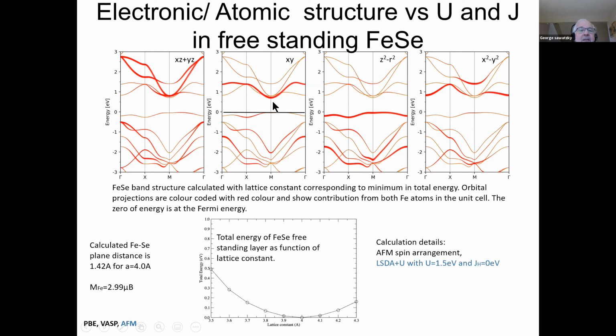So the gap here is almost 1 electron volt. Okay. And you have this very flat band right at the Fermi level. And it has a very strong z-squared character, not xy, not yz, xz, but z-squared. Again, the lattice constant now is very large. It's 4 angstroms. And when you stretch things out horizontally, the vertical distance will decrease also, okay?